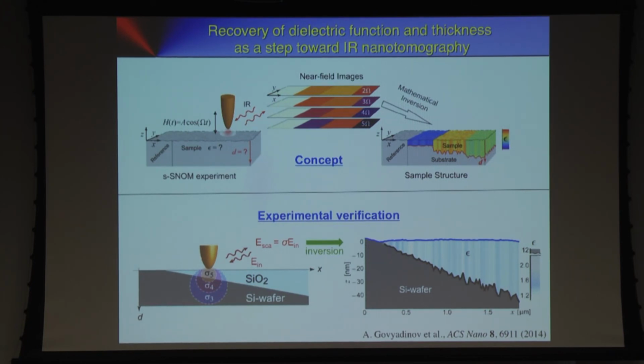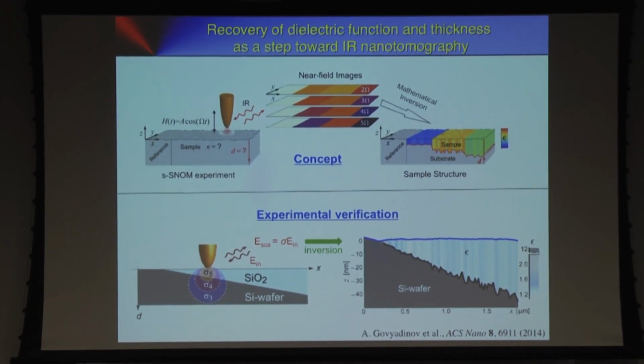How about combining some concepts like OCT, optical coherence tomography, with this technique? Because in OCT you have the depth profile. Yeah, but the point is that this range here is 40 nanometers, right? We are deep sub-wavelength scale. We cannot look deeper. We could look deeper by making larger tips, but then we lose resolution. If you go to 1 nanometer sharp tips, we wouldn't look deeper than a few nanometers. So that's a drawback. Spatial resolution and depth resolution are coupled. So this is a surface-sensitive technique that has the capability to probe a shallow subsurface layer, which is always on the size of 2 or 3 times the tip radius, but not more.